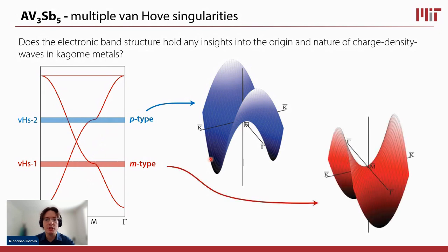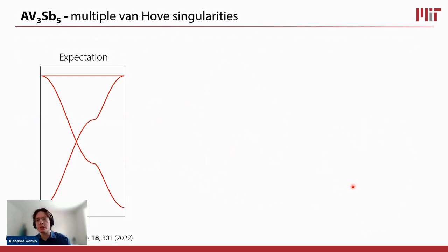So these two saddle point-like dispersions at the endpoint. And if we look at these two Van Hove singularities as a function of two-dimensional momentum, so not just as a function of one-dimensional cuts in the Brillouin zone, but really as a function of 2D momentum, we see that they have this very characteristic saddle point-like dispersion, where the dispersion of the bands is concave along one direction here and is convex along the perpendicular direction in the case of the upper Van Hove singularity. And for the lower Van Hove singularity, it's essentially rotated. So we see a concave dispersion along this direction, which is K point to M point to K point. And then along the orthogonal direction, so from gamma to M back to gamma, we see a convex dispersion.